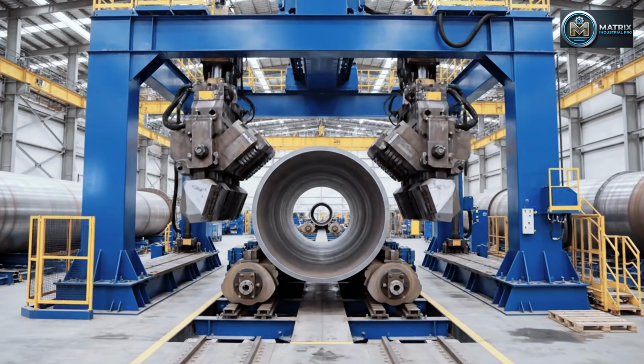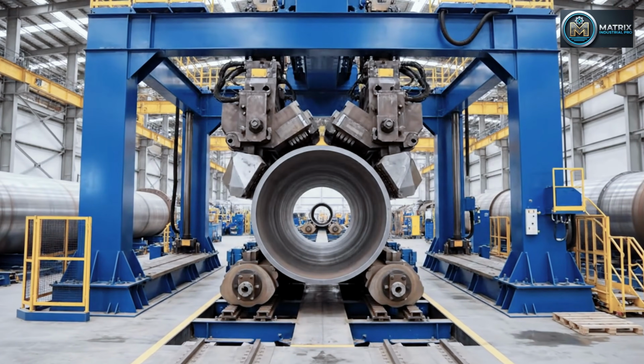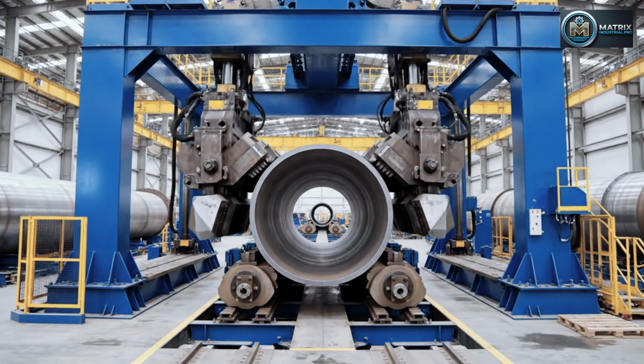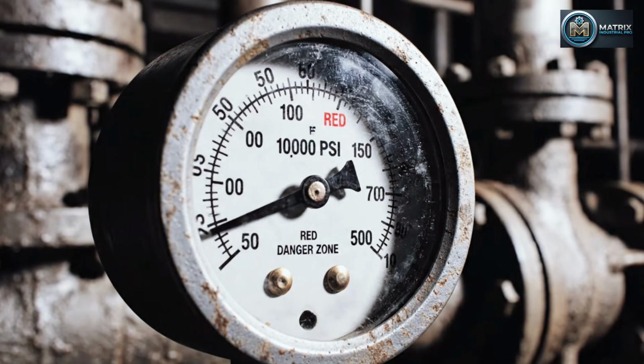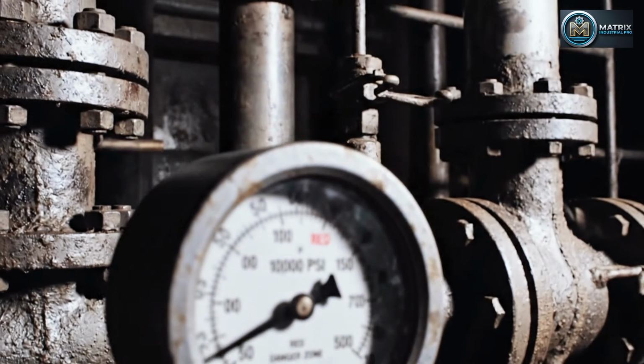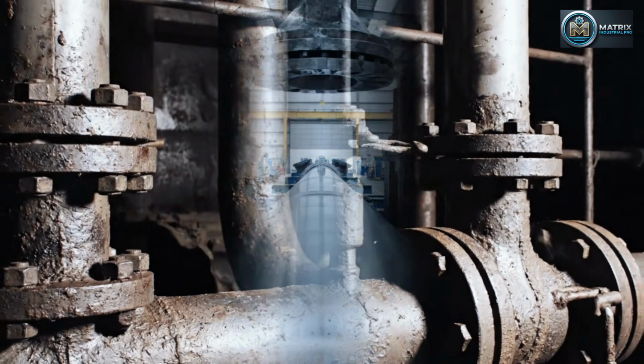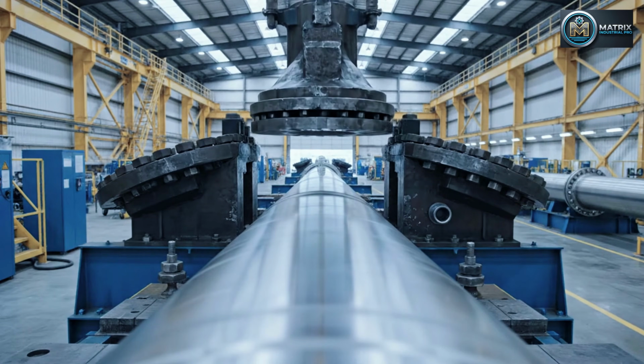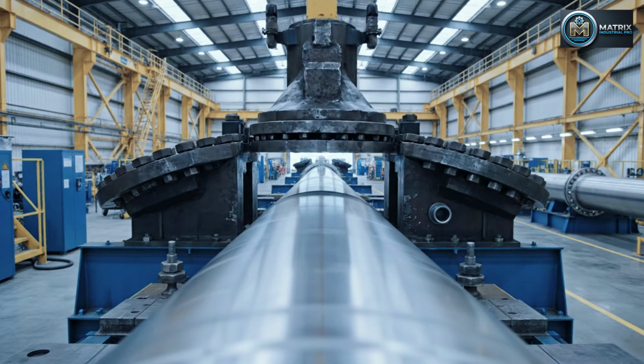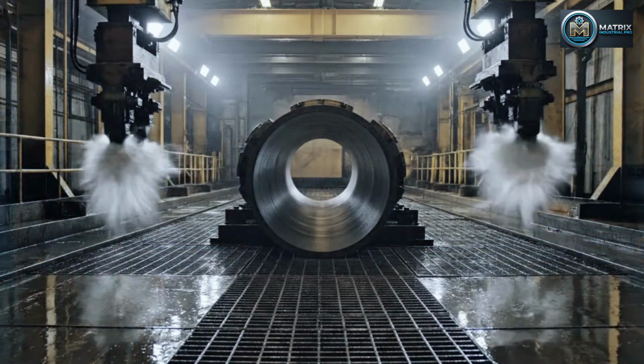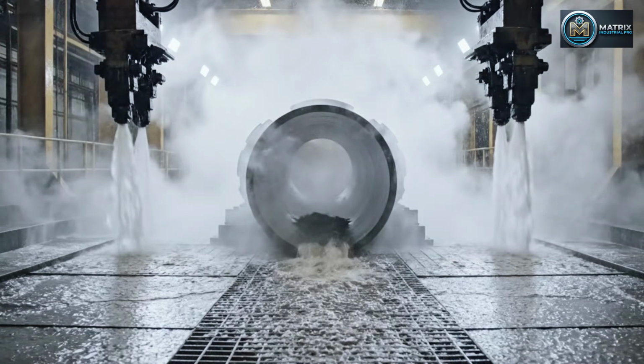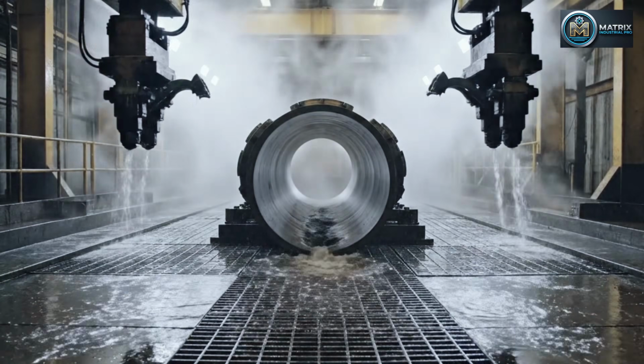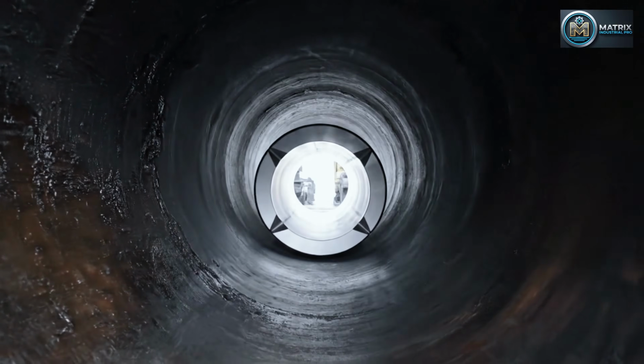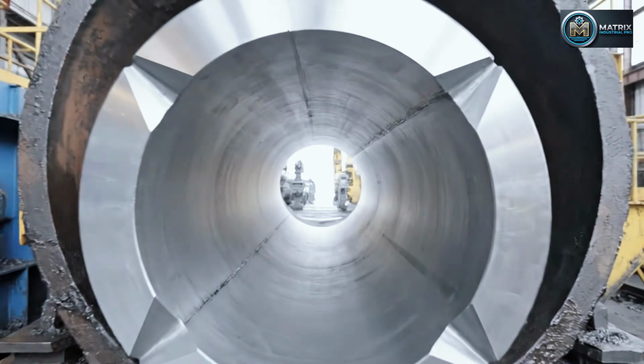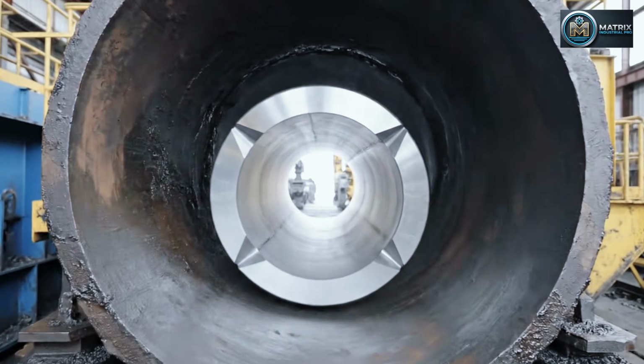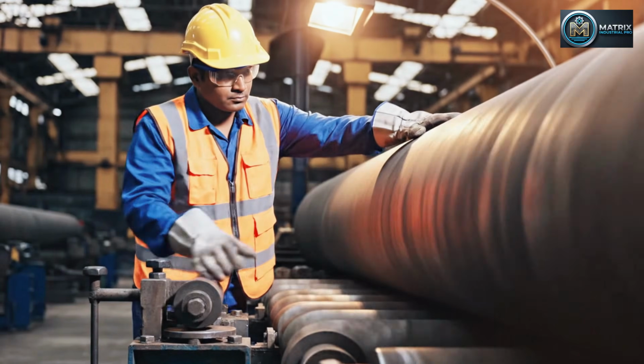Every single pipe must survive the hydrostatic pressure test. Water is pumped in until pressure exceeds 10,000 psi. It holds the pressure for 10 seconds to prove integrity. The pressure is released, and the pipe is certified. A drift mandrel is pushed through to ensure the inner diameter is clear. Human eyes give the final approval.